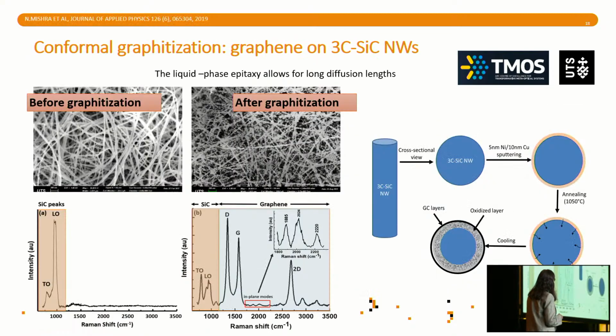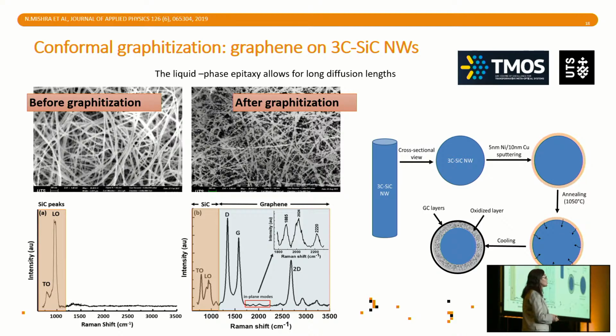The same trick can be used to graphitize silicon carbide nanowires. In this case, it was a very, very messy forest that we got from collaborators, but we wanted to prove the point, and it proceeds the same way. And again, we have a very thin, few nanometers oxide, silicon oxycarbide, in between the graphene and the silicon carbide core, which is very interesting optically speaking.